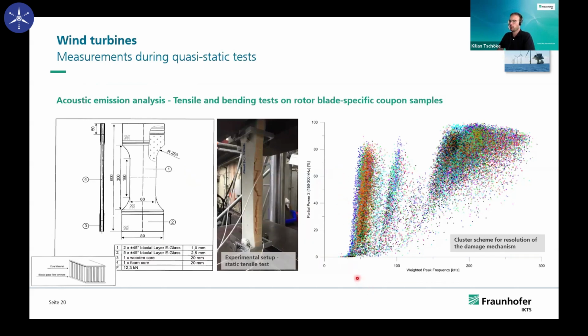How do we get information what type of damage we have? Well, usually we start with coupon tests. In this example here, we have done tensile tests on coupon samples made of the same material as the rotor blades, and then by destroying these coupon tests, we collect the acoustical data and analyze the damage. With these coupon tests, we get the database for these materials, for these rotor blades, where we can see clusters in the frequency power domain. Power here is like the amplitude or the energy in your signal.